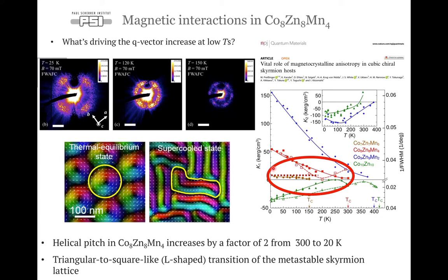And again, in this work done with ESR, we have seen that the cubic anisotropy constant for the 884 material, here it's in red, also increases at low temperatures. So maybe the occurrence of this cubic anisotropy and its development over low temperatures promotes the helical pitch change by a factor of 2 from 300 to 20 K in 884. And maybe it also can drive the triangular to this square-like Skyrmion lattice transition for the metastable supercooled Skyrmion lattice state. Let's see.